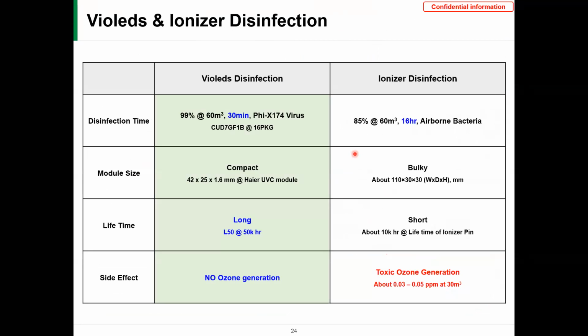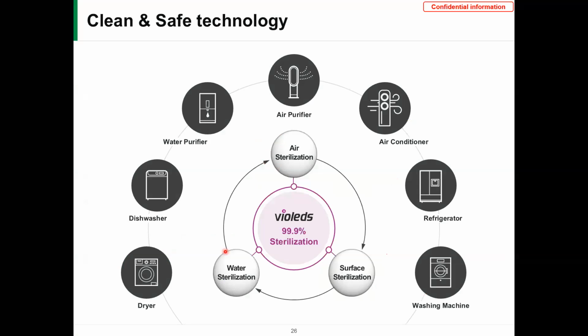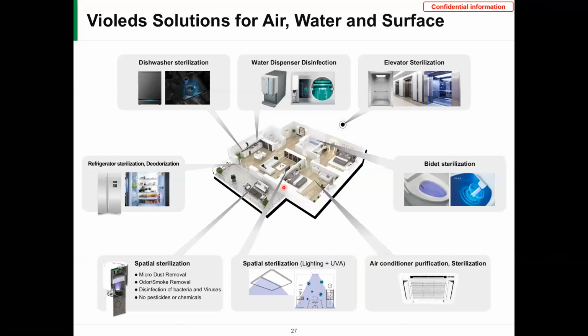Some home appliance companies use ionizer technology, and ionizer technology generates some ozone. Our technology produces no ozone, and the lifetime is longer than ionizer technology. And our LED can disinfect bacteriophage in a very short time, like 30 minutes, compared to ionizer technology, which takes 16 hours for 60 cubic meters. And we can use it in almost every home appliance.